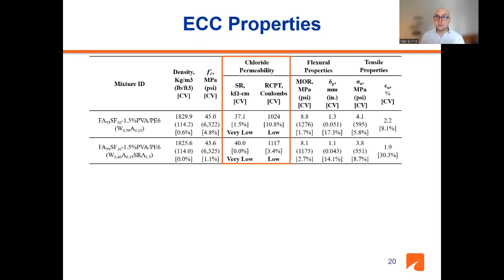So as you can see, the surface resistivity is quite high. So this falls in the category of very low chloride ion penetrability. And the rapid chloride permeability test results, as you can see, is about 1,000 coulombs for these materials. So again, very low permeability systems.